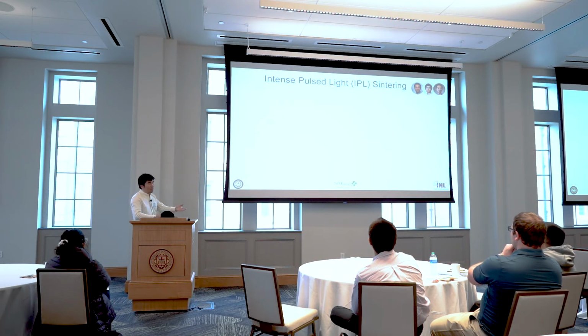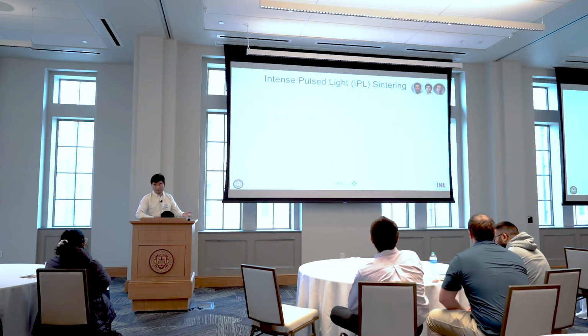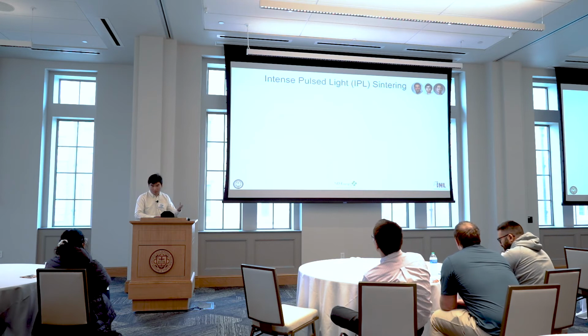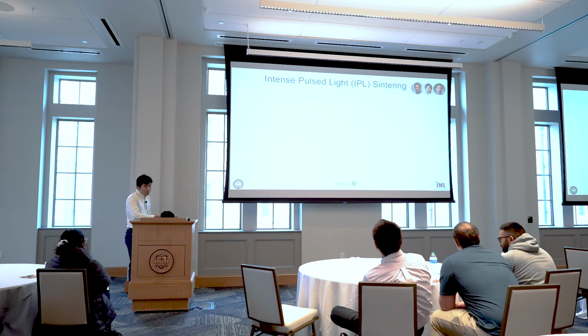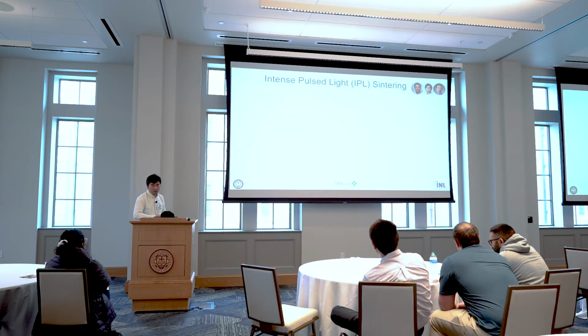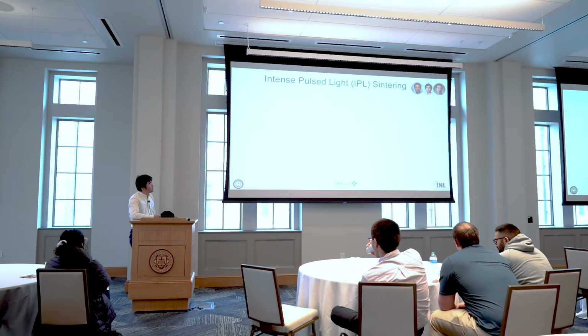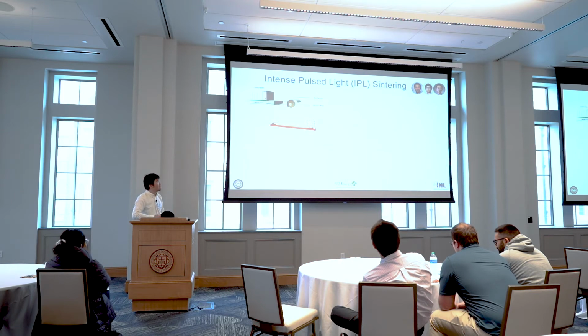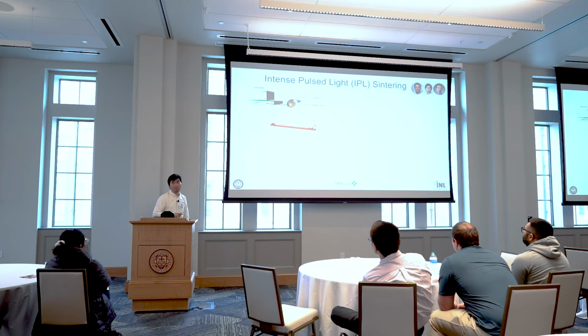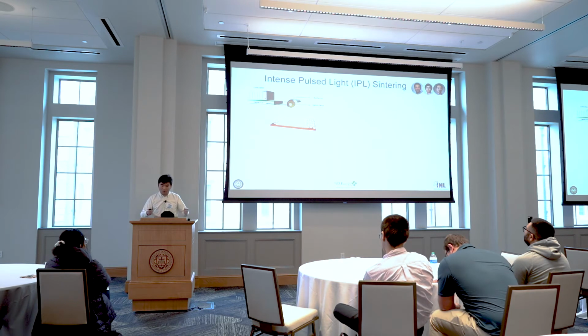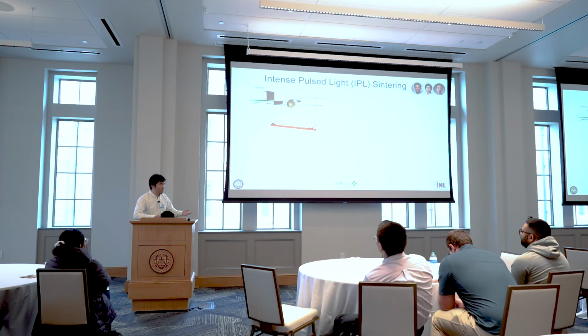So I said put it in the oven and bake it for a few hours. That's one way of doing the sintering. It's not high throughput. It takes time and it takes a lot of energy. But there is another way to do sintering, and it's what Professor Yan Liang's group is doing. It's the so-called intense pulsed light sintering. What it does is instead of using the oven to provide the heat, it shines a light. And the light intensity is very high, and you can locally heat up the sample, the film, and then the same thermal process happens. Okay, boundaries merge, solvent evaporates, and then we hope that we can get the same result as thermal sintering.